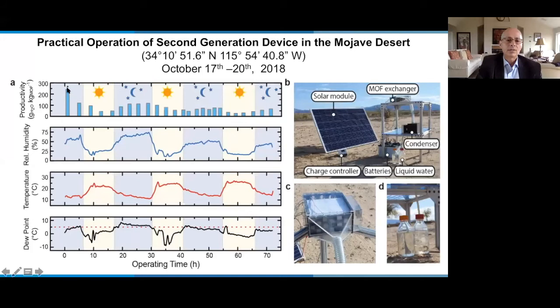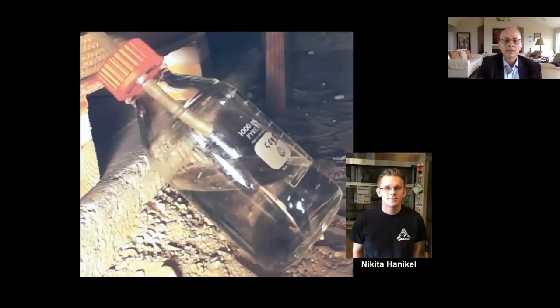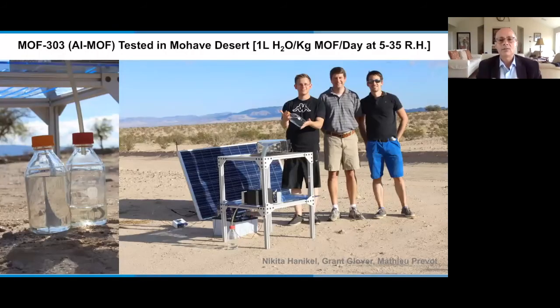Ignore this one because that's the water in the MOF leaving Berkeley, where it's a little bit more humid. So once the system is going, you can see that it's harvesting water at night and during the day, even at humidities as low as 7% relative humidity. And that's really the advantage of these MOFs. This is a real-time picture of water being harvested using that device. You see here drops of water being collected. So using this MOF, we can harvest 1 liter of water per kilogram.